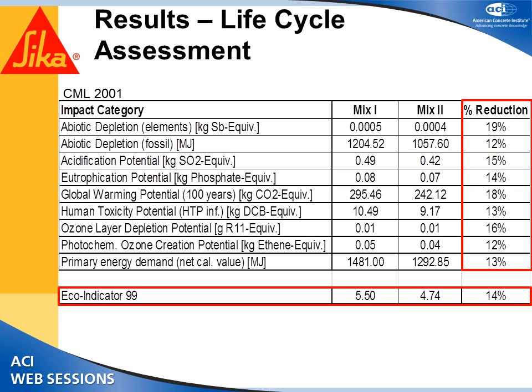And when the other method was used, which is the Eco-Indicator 99, which is also similar to CML 2001, but it gives you an average number, giving weightage to different categories. It was found that mix 1 was 5.5 and mix 2 was 4.74, which means a 14% reduction in the life cycle assessment.